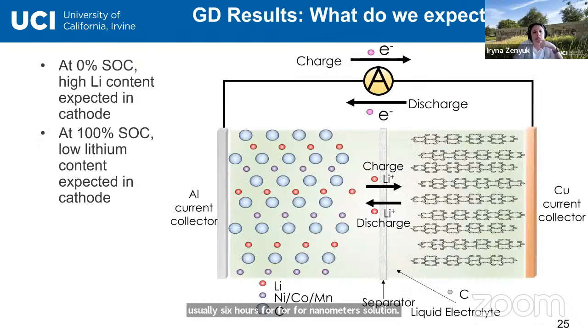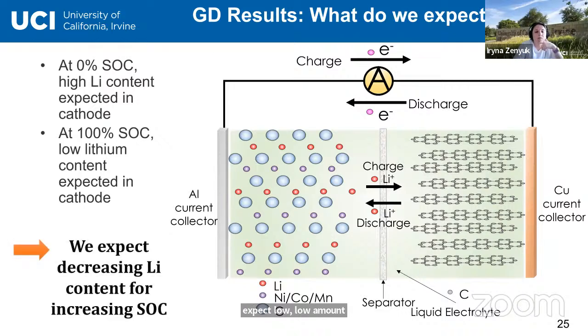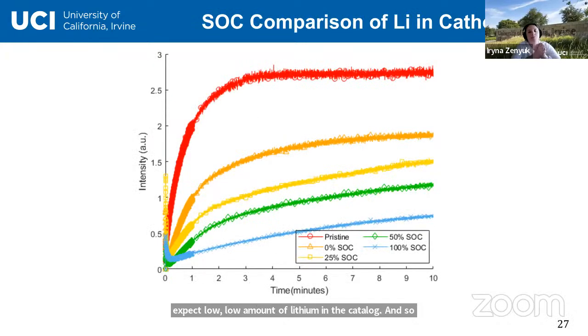So what do we expect to see? If you think about a battery being discharged or charged, at 0% state of charge we expect high lithium content in the cathode, and at 100% state of charge we expect a low amount of lithium in the cathode. Looking at the profiles obtained while the cell is being discharged from the pristine sample, time correlates roughly to micron resolution. You can see here within 1 micron we collected a lot of information, and the steady-state lithium profile is achieved somewhere after 3 microns or so. As state of charge increases, we have less and less lithium present in the cathode of the material.